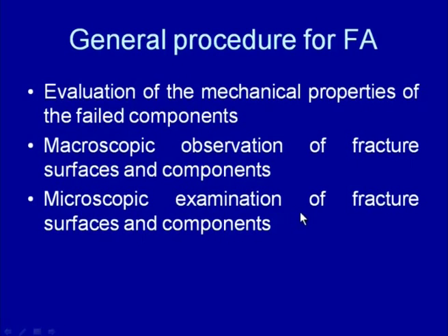Then the microscopic examination will indicate the kind of microscopic mechanism which was involved in fracture of the component. These mechanisms are mainly of 4 kinds. One is the dimple fracture, where very conical shaped cavities are observed on the fracture surface. The dimple fracture shows whether the fracture is ductile or brittle. So the dimple fracture indicates ductile fracture, and then brittle fracture will be indicated by features like intergranular fracture or the presence of cleavage facets.